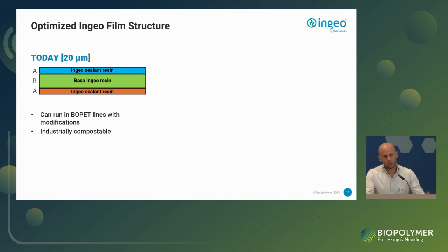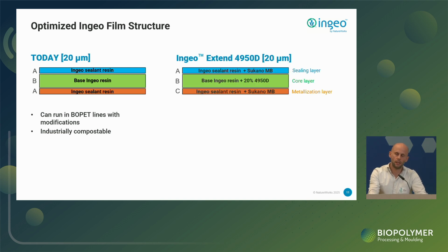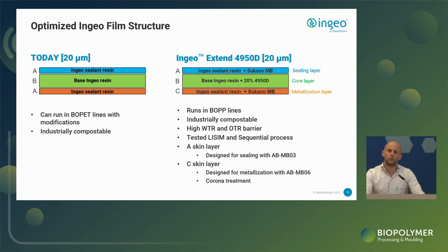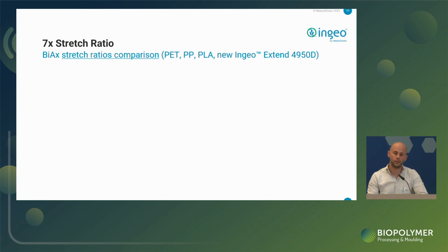And going now into the technical details, what you see here on the left-hand side is a typical BOPLA structure, 20 micron thickness. You have the core layer and you have outside the sealant layers. And the new development contains in the core layer 20% of our new Ingeo Extend grade. And then in the sealant layers, you have specially designed master batches from Sukano. Those are designed to not affect the transparency of the film, but to adjust the anti-blocking properties, to adjust the COF, so the coefficient of friction, and at the same time to not decrease the performance in terms of metallization and lamination behavior and adhesion of such technologies.